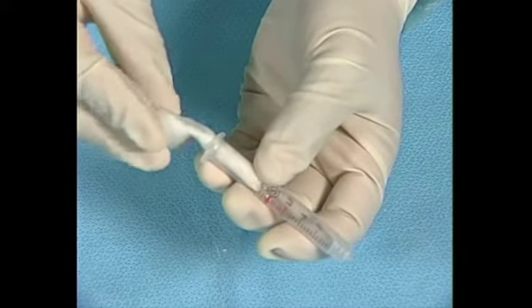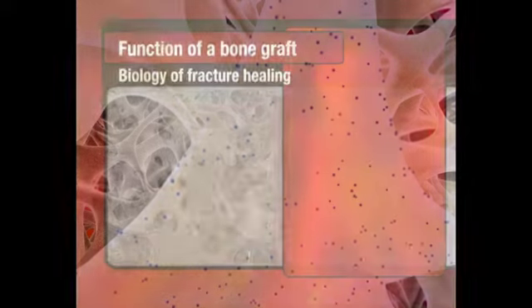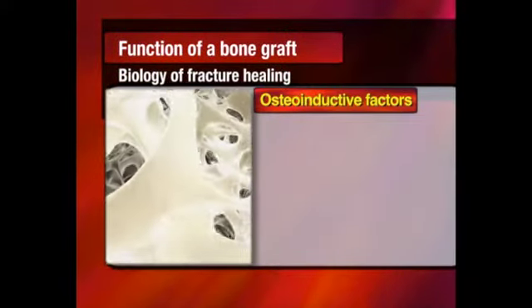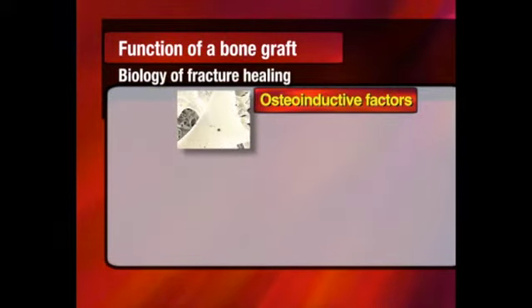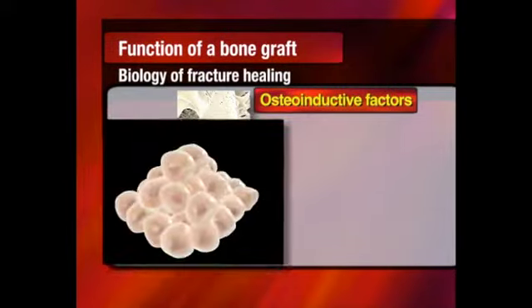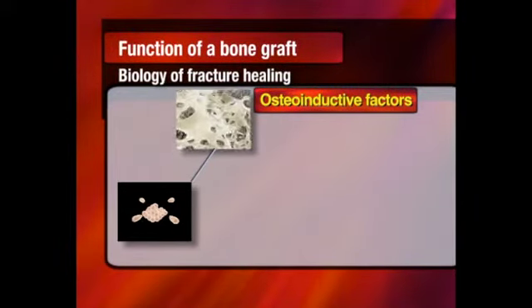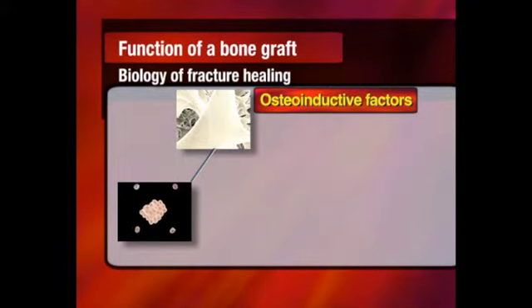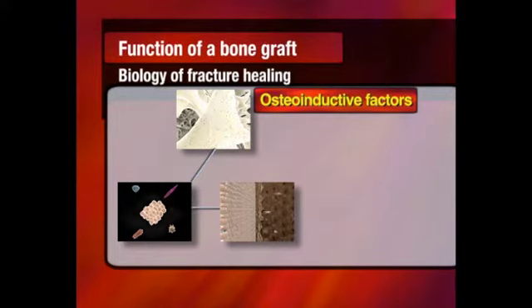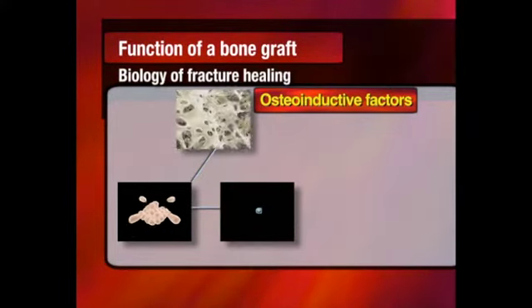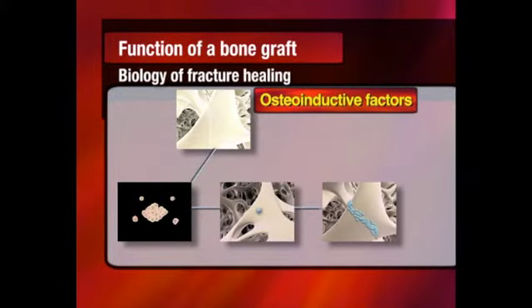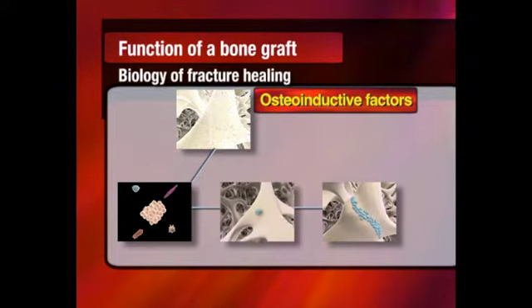The appropriate migration of cellular components to the site of a fracture or bone graft is crucial for the fracture healing cascade. Osteoconductive bone graft substitutes allow migrating pluripotential stem cells to populate a fracture site and start new bone formation. Modulating this entire process are the osteoinductive factors. These proteins may provide the chemotactic and/or mitogenic stimulation to the osteoprogenitors. The fracture healing cascade is enhanced by some of these osteoinductive factors which promote the migration of the pluripotential stem cells to the fracture site through a chemotactic process. In addition, osteoinductive factors may be involved in cell proliferation through a so-called mitogenic effect.